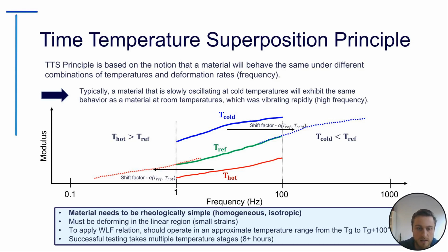The samples also must be deformed in the linear region, so small strains must be applied. And to apply the WLF equation, it should be in the approximate temperature range near the glass transition temperature and 100 degrees above the glass transition temperature. So you're sort of limited in your temperature range as well.